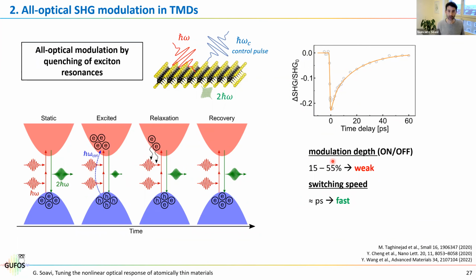I have to admit that now there are papers that show much larger modulation depth, close to 90, 99%. However, in that case, the limitation is that you can achieve this modulation only for a very specific photon energy. Because in order to get this modulation, you need to be very close to the exciton resonance. Whenever you are far from the exciton resonance, there will be no modulation anymore. So either you want a large modulation depth, but then you are very limited in bandwidth, or you reduce the modulation depth and you can do it almost for any wavelength.